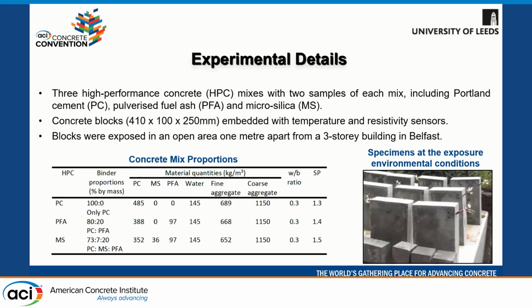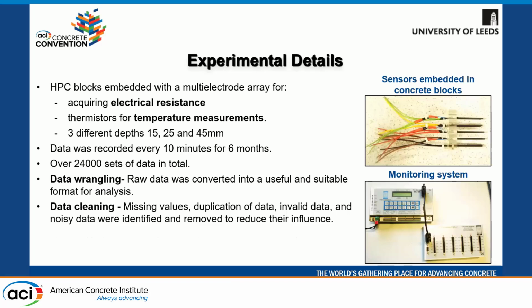These blocks were cured for 3 days and then kept outside in an open area on the 4th day. These blocks were exposed 1 meter apart from a 3-story building in Belfast. These blocks were embedded with multi-electrode array for acquiring electrical measurements and thermistors for temperature measurements. They were kept at 3 different depths, 15 mm, 25 mm, and 45 mm depth. The data was recorded every 10 minutes for 6 months in the data logger, and we gathered over 24,000 sets of data in total.